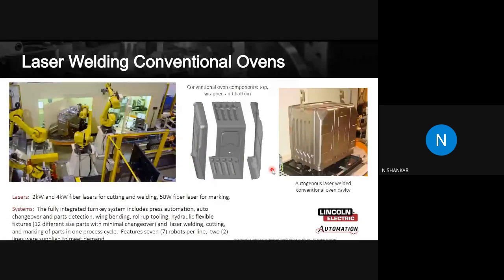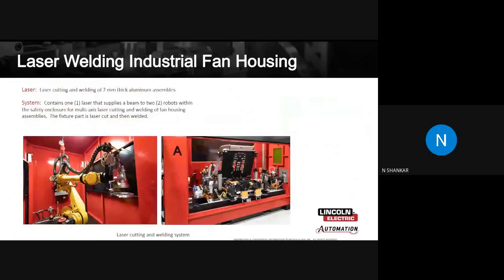Here is a conventional oven I was talking about. There are 3 parts to be welded. These are blanked, punched, and then welded. Since it's for domestic use, it has to be a pretty good, neat, clean build, which was achieved with laser applications. Here we used a 2 to 4 kilowatt laser power source for this welding application with 3 robots doing this. Industrial fan housing is another example where a laser welding solution was used.